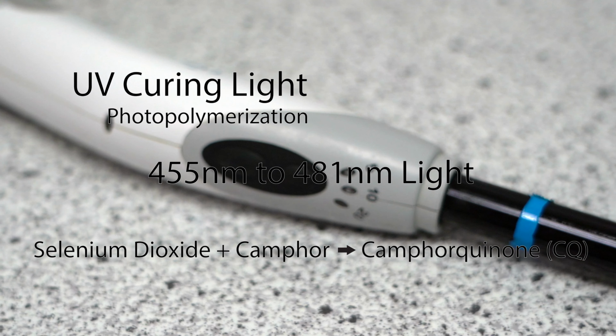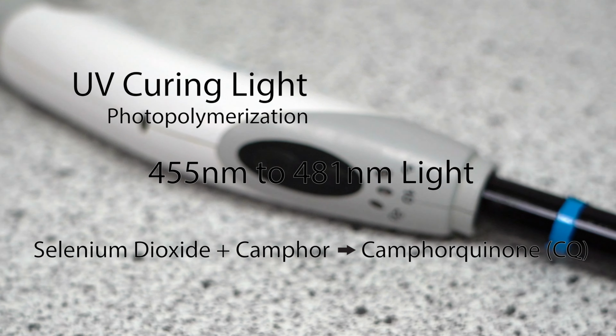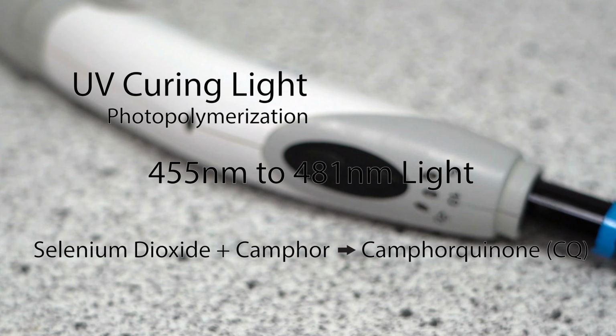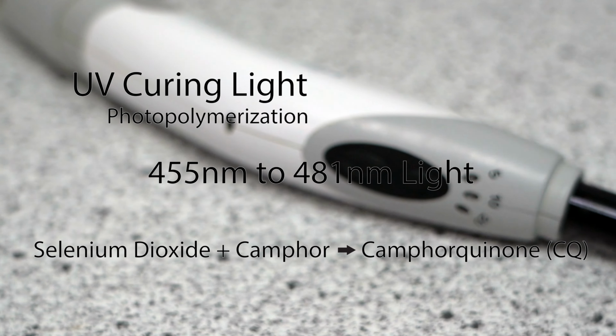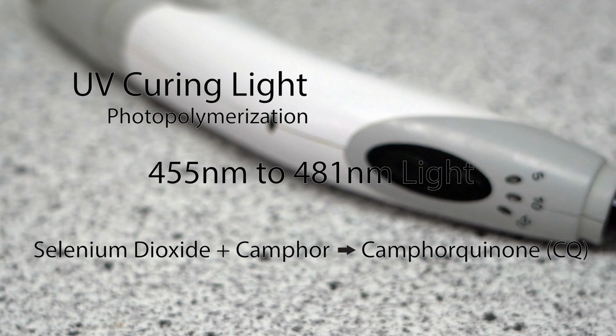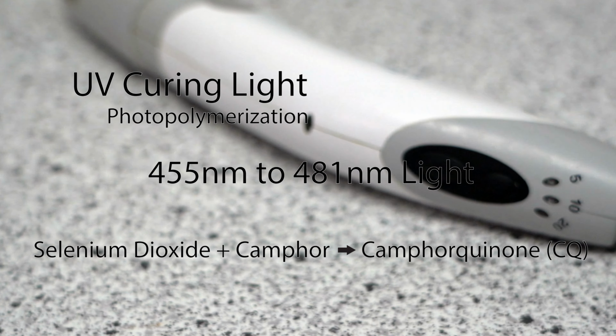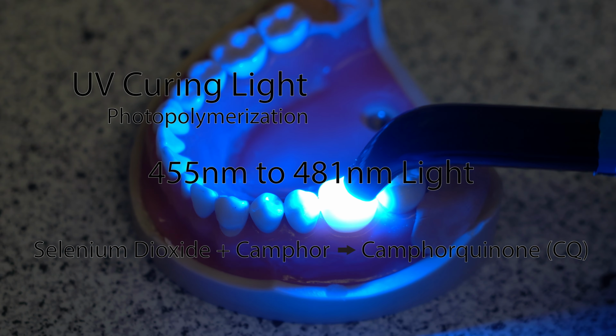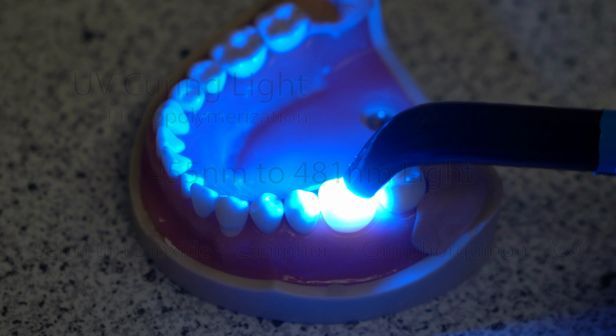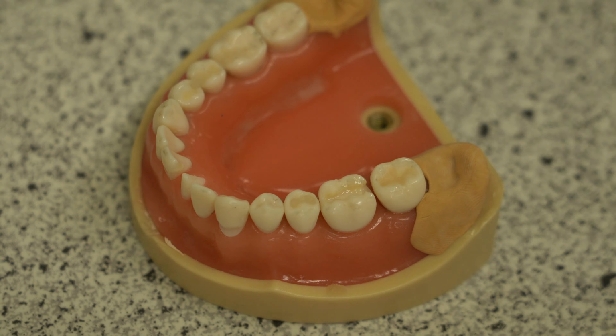resins and bonds. The peak absorption range for CQ is from 455 to 481 nanometers, with peak absorption at approximately 469 nanometers. It takes 20 joules per square centimeter, or 20 joules of light energy deposited on the area of resin, to properly cure most materials.